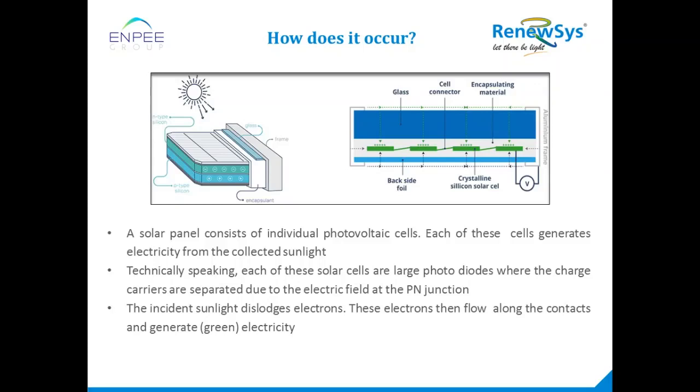And the performance of a solar cell means once the PN junction is completely damaged, it no more acts like a photovoltaic cell. It simply acts like a metal or a conductor kind of stuff, where there is a direct path. So even if sunlight falls onto that solar cell, it cannot generate electron hole pairs. Even if it generates electron hole pairs, there is no electric field to separate the electron and hole. So this is the effect we are going to have during a PID.